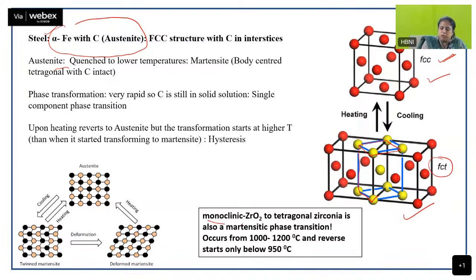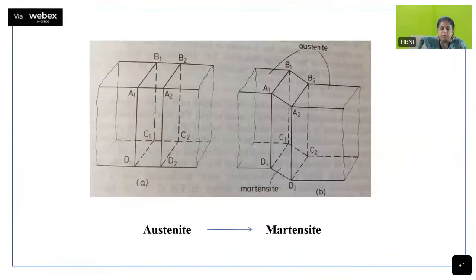This is also shown in monoclinic zirconia to tetragonal zirconia. Now, this is one material which I have worked with a lot. So, monoclinic zirconia undergoes transition to tetragonal zirconia. It starts at 1000, goes on till 1200. Okay. And if you reverse it, that is, want to go from tetragonal to monoclinic, it will start only below 950. So, that much hysteresis from 1200 to 950 is observed. And then, as I told you, it starts from one side and moves on. It just doesn't happen all of a sudden.